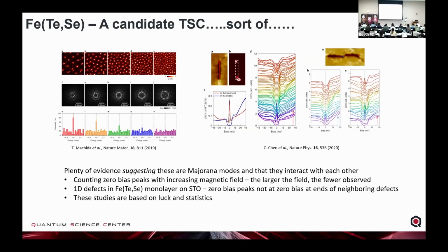And there are also other systems where you can put just a monolayer of this on strontium titanate. And you can see on one end what looks like a Majorana mode. But in areas where you see these 1D features and the Majorana modes next to each other, they start to move off of zero energy, once again indicative of interactions between these modes.